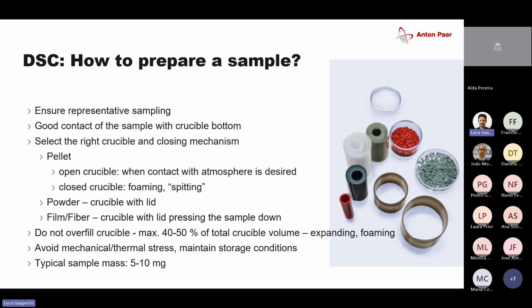What's very important to ensure is a good contact of the sample with the crucible bottom, with the sample holder, because this is actually the path of energy from the sample contact with the crucible bottom onto the sensor, where I have the thermocouple that senses the temperature and temperature changes. And if I do not have a good contact, then of course I'm losing information. My peaks are getting broader and shallower, and then my resolution goes wrong. So good contact of the sample with the crucible bottom is one of the most crucial things.